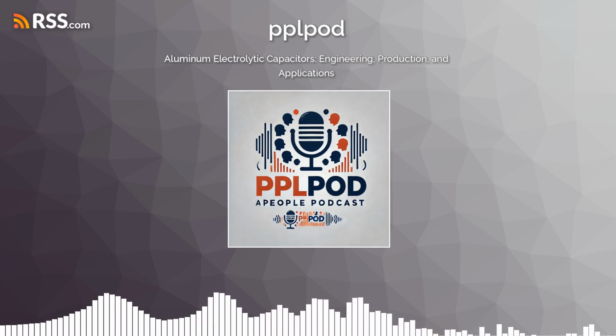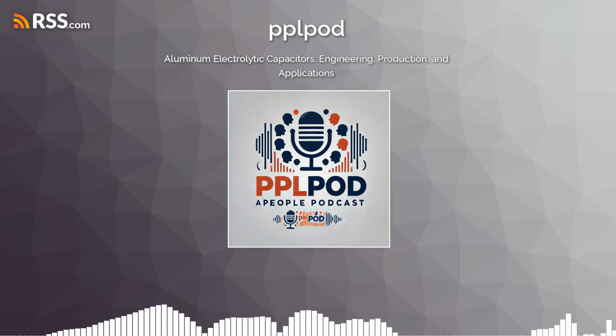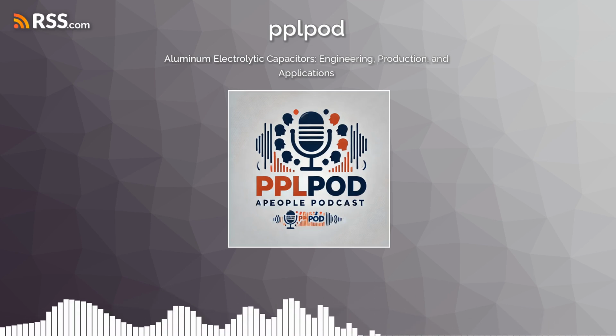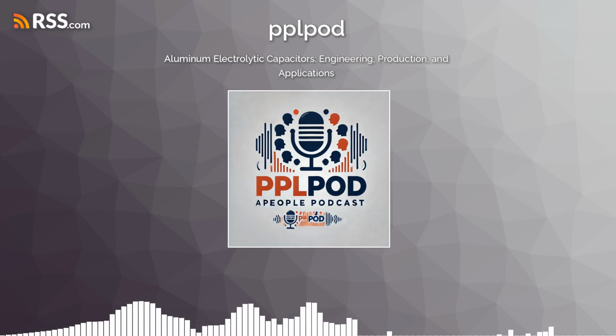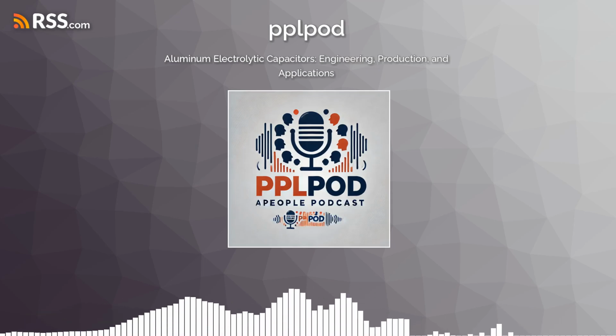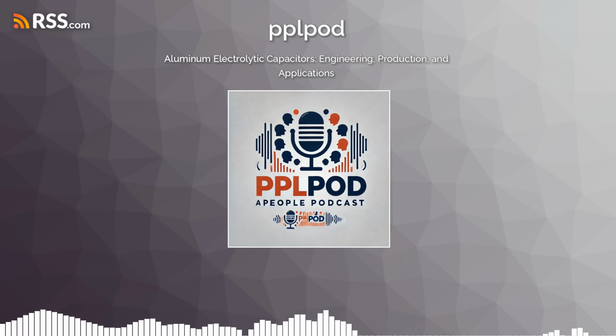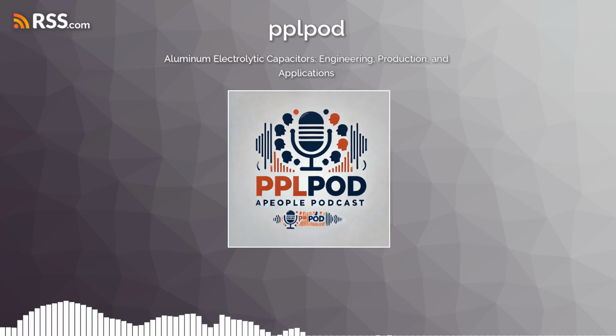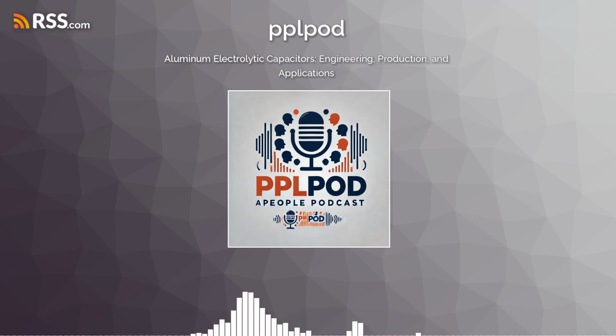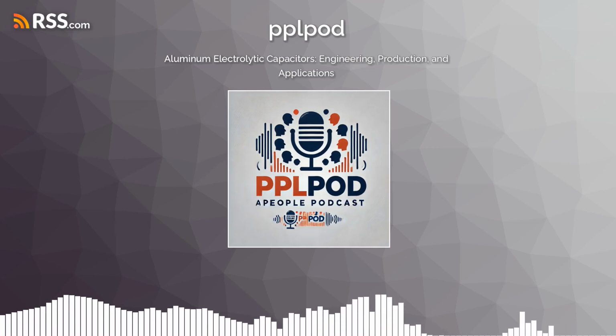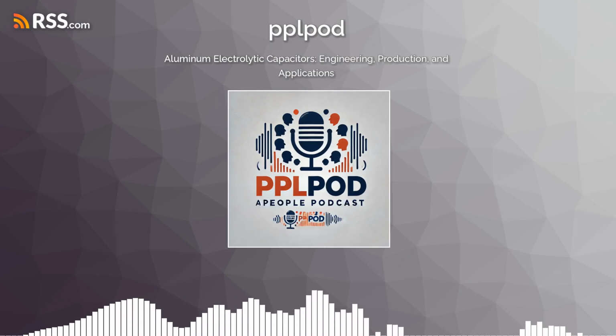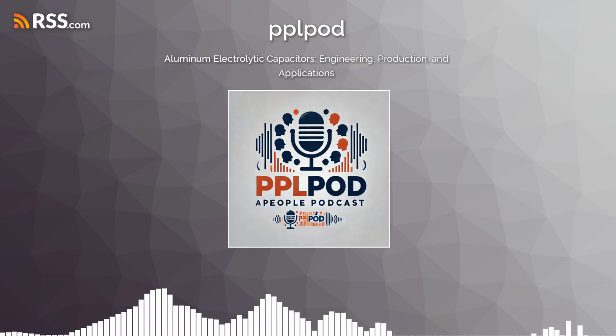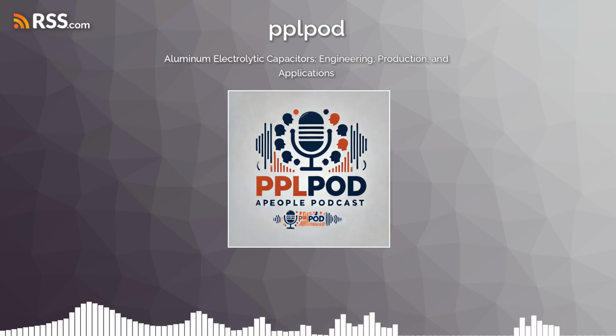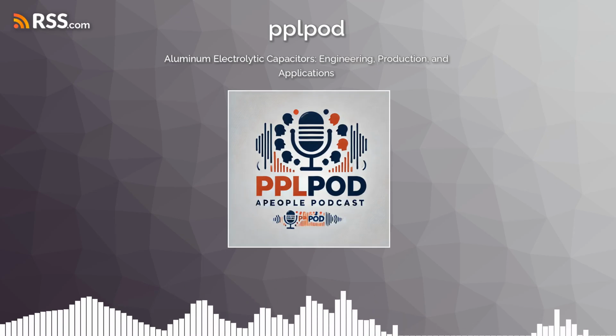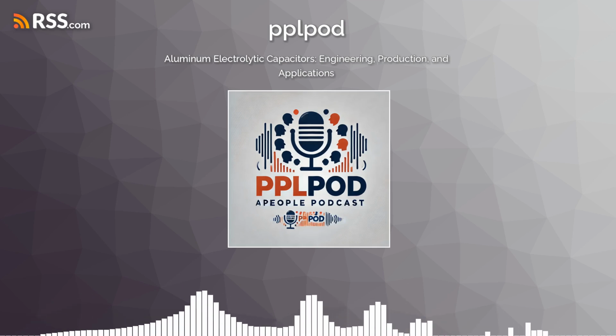Yes. When a wet aluminum capacitor just sits on a shelf, completely unpowered, with 0 electrical volts pushing through it for several decades, the liquid electrolyte, which remember is a mildly acidic soup, just sits there and very, very slowly eats away at our precious aluminum oxide layer. The useful rust just dissolves away. It does. With no leakage current to trigger the self-healing process, the thin insulation wall just gets thinner and thinner until it's basically bare metal again. The protective wall just crumbles into the moat.